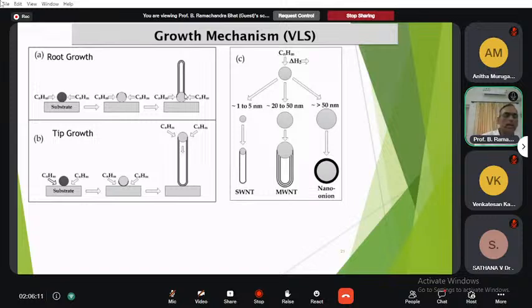Now you have another method, that is the tip growth method or mechanism. In the tip growth method, as I said, the hydrocarbon dissolves in the nanoparticle, and since the interaction between the metal nanoparticle and the substrate is weak, the precipitated carbon lifts the nanoparticle away, and thus you have the metal nanoparticle on one side of the nanotube, and that's why it is called the tip growth method.